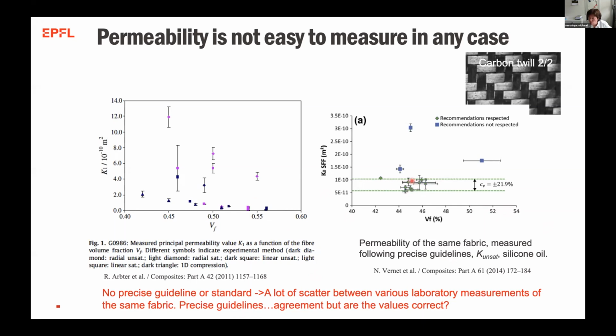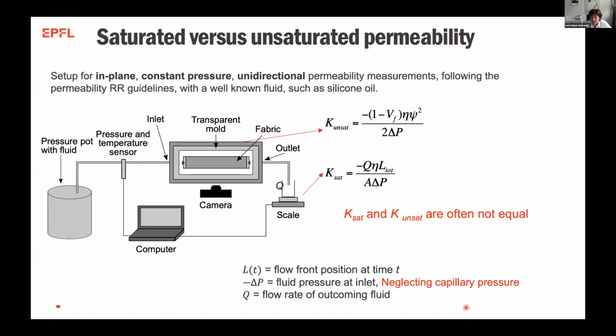Now, are these values good? Are these values the real permeability of the fabric, or do we all agree on the wrong value that we have been measuring because we measured K unsat and silicone oil? That's a main question. So we can always say, well, if we at least all agree with the wrong values, we can compare each other and compare our methods. And if I increase the permeability of a fabric, I can measure it. But if we want to really know what we're measuring, we may need to ask ourselves a bit more questions.